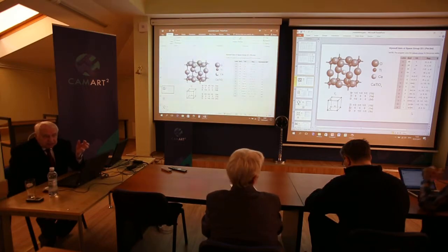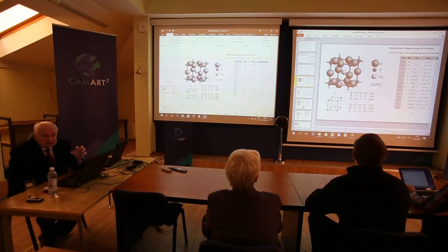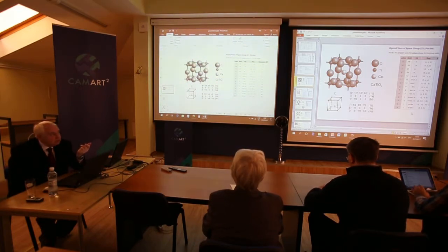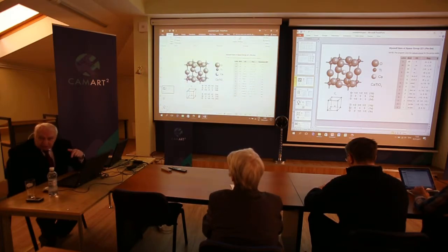In this case, these sets of points are A, B, C, and so on, and the crystalline structure consists of the lattice, Wyckoff positions, and the distribution of atoms. There is more than one possibility for where atoms occupy Wyckoff positions, but Wyckoff positions are occupied by atoms according to the chemical formula.